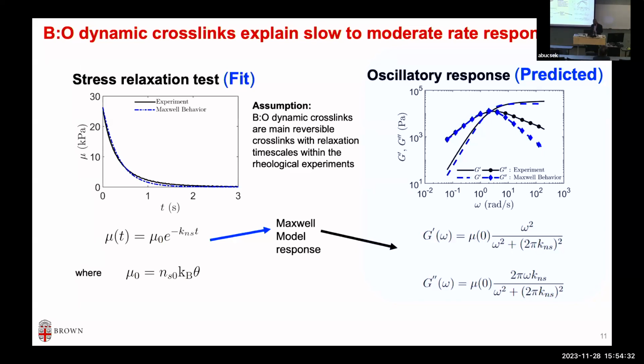So what that tells us is that for this strain rate range, where we are looking at very slow quasi-static to moderate rate in the oscillatory rheology, the boron oxygen, the dynamic crosslink, is the dominant mechanism with the first order kinetics and does a very good job. So that kind of shows that this assumption in that range works quite well. From this one fit, we can predict this.